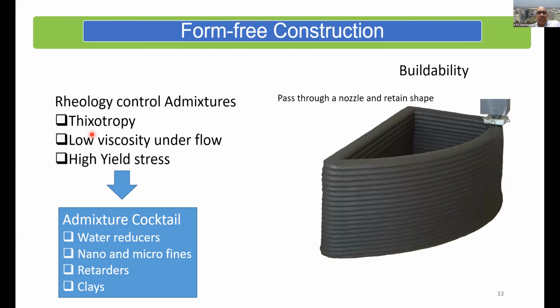Now we need to understand really the rheology of this concrete, which takes us into the domain of understanding what is known as thixotropy. This is a rheological property that talks about the internal structure within the cement paste, and which we can manipulate to start creating or start stacking up layers as we print them. We need a material mixture that is low viscosity under flow. As I pressurize it, it should flow easily and should have a high yield stress. So that means it should keep its shape once it comes at rest. And this is possible by using, of course, water reducers. We use a lot of nano and micro fines because these help enhance the rheology, and retarders. And now we are also starting to use clays into concrete because they give us that fine rheology control that helps us build a structure layer by layer.